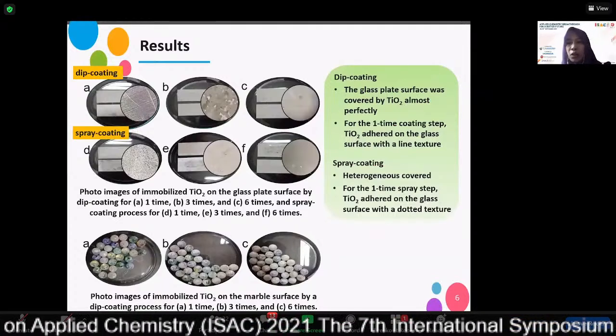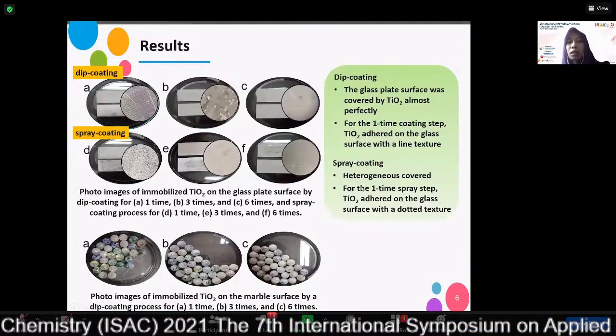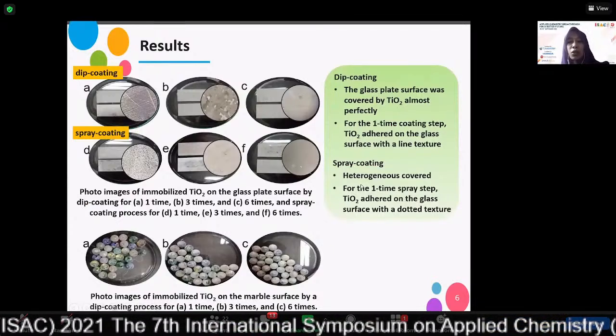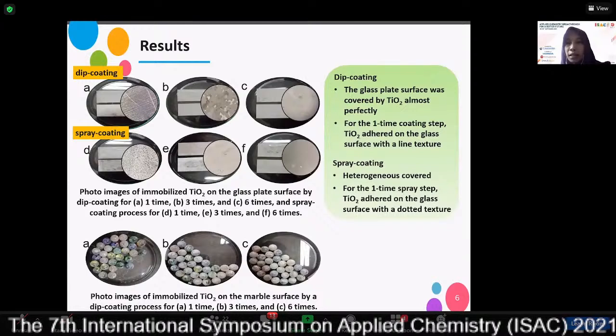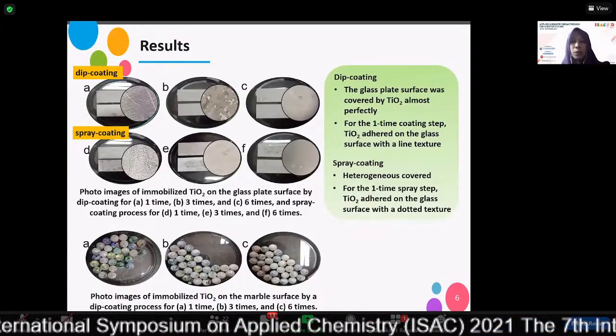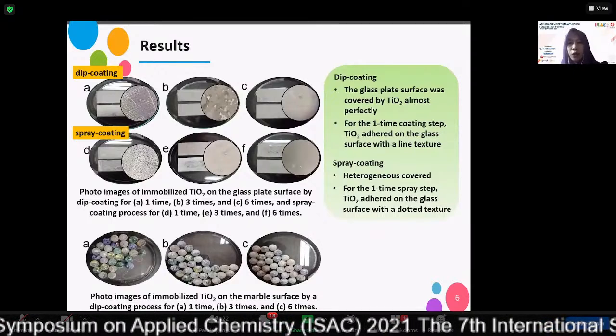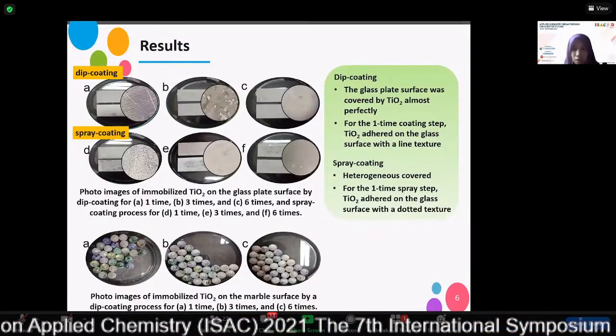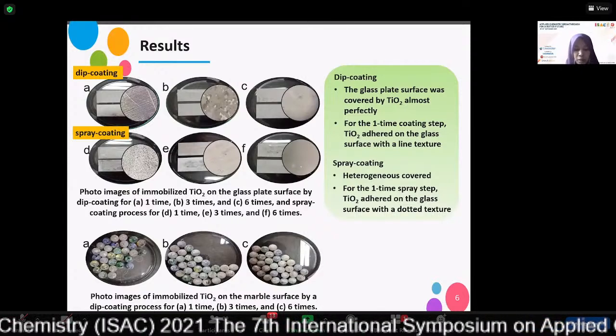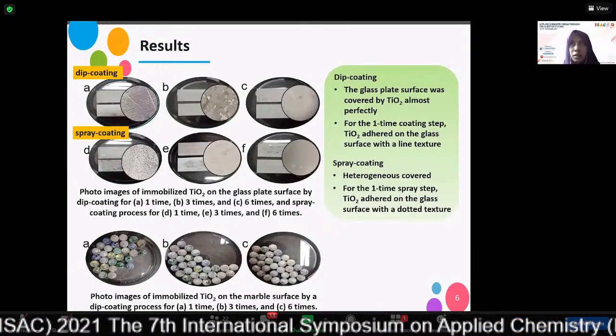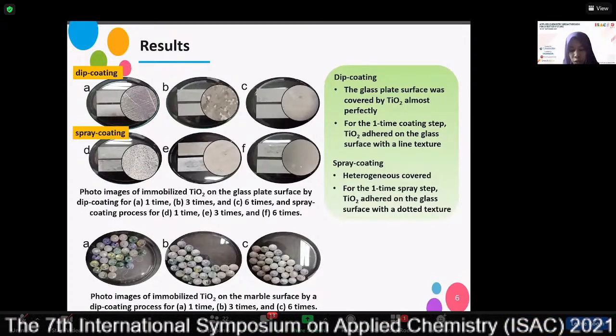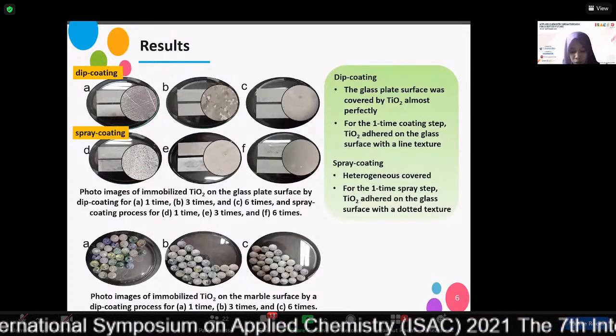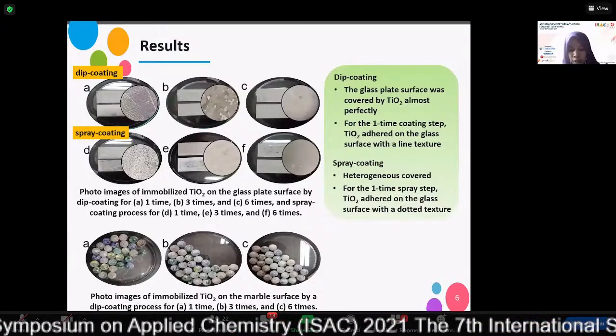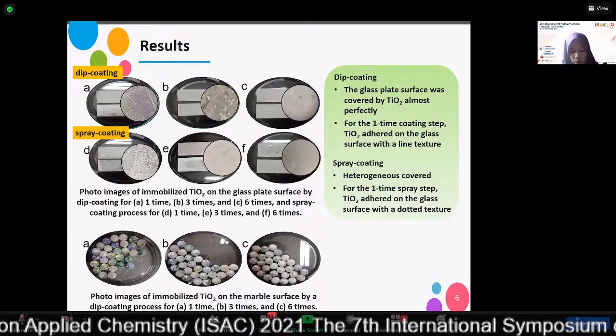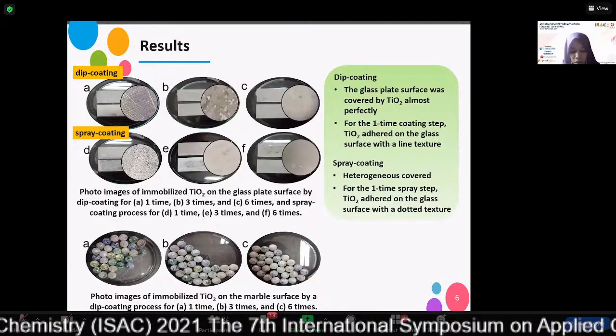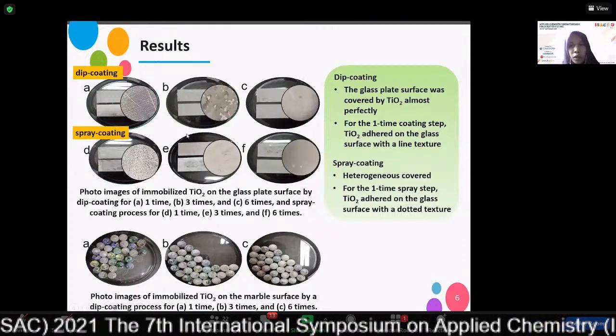And for spray coating, the TiO2 had a heterogeneous coverage of the glass surface. And for the one-time spray step, the TiO2 adhered on the glass surface with a dotted texture. And this becomes thicker when the coating was added, but dip coating and spray coating processes were successful in adhering TiO2 on the glass plate.